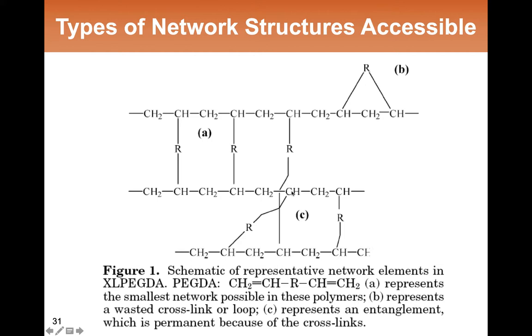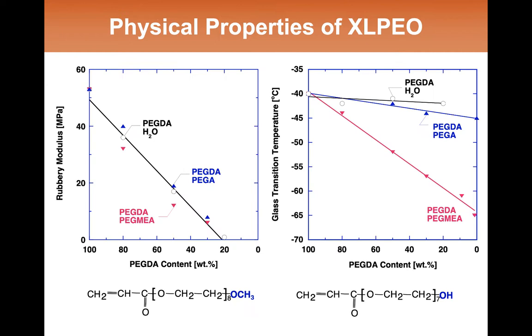And as a result of this, one can change the structure of these networks by varying the conditions under which they're polymerized, and we'll talk about that in just a second. The first thing that I'd like to show you is mechanical property data showing copolymers that have been prepared with just polymerizing the diacrylate or the cross-linker. These are all rubbery materials with glass transition temperature well below ambient.